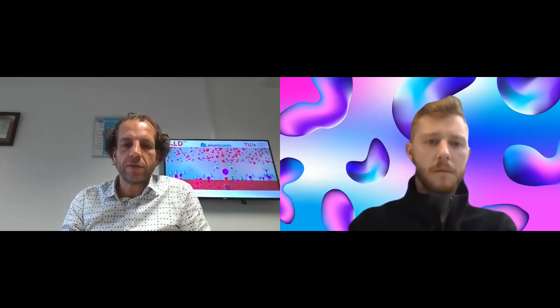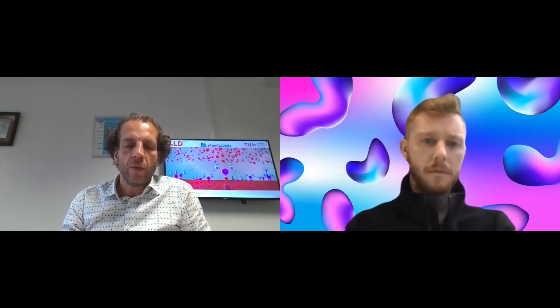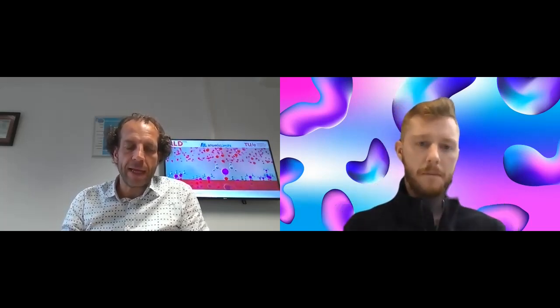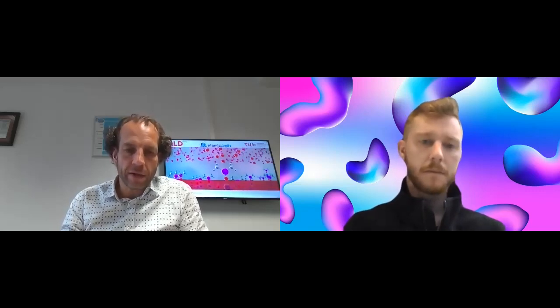We did a study on this. We published this 2 years ago, I think. The student just graduated, where we demonstrated that plasma ALD can still be conformal up to aspect ratios of, I think we found out, 800. Wow. This is another thing that maybe is good to mention, because often people think that plasma ALD is not conformal. Well, if the plasma ALD process is driven mostly by the radicals, then for some materials, plasma ALD can be extremely conformal. A very nice example is silicon oxide, and also titanium dioxide can be very conformal even with plasma ALD, and you can reach aspect ratios up to 800 if you work with a sufficiently long plasma exposure time.